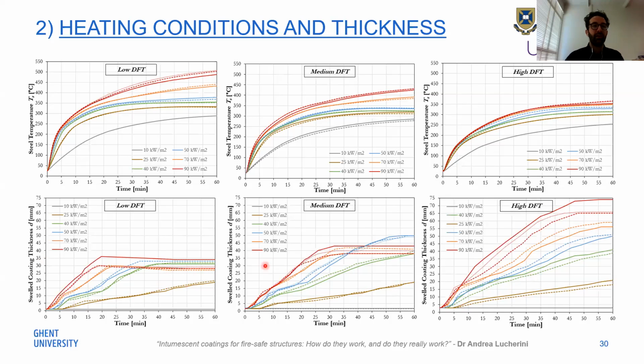But what's interesting as well is that in the case of low DFT, when you have swelling, all the temperatures tended to a range between 300 and 350. Then, when we have 1 millimeter DFT, you can see that in the case of the red curve for 90 kilowatts, around 20 minutes the coating stopped, the swelling stopped. And the temperature in that case, which was around 350, started increasing above this threshold.